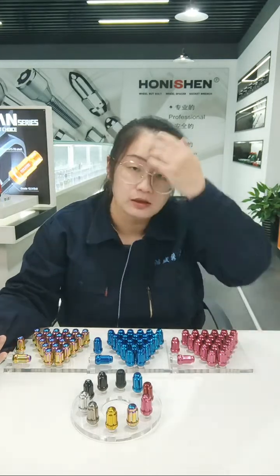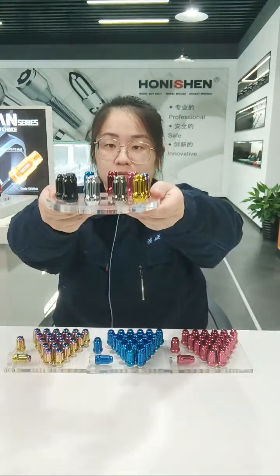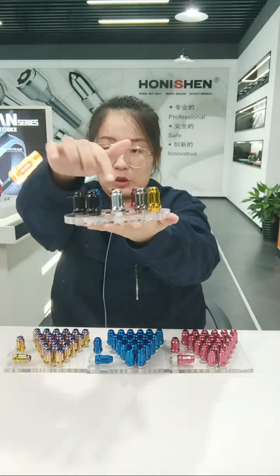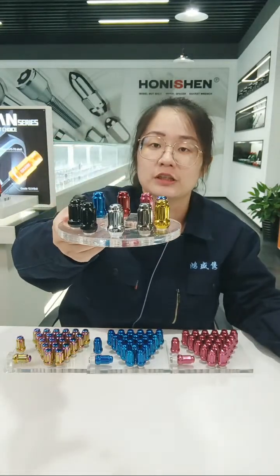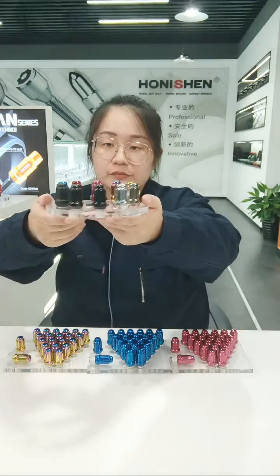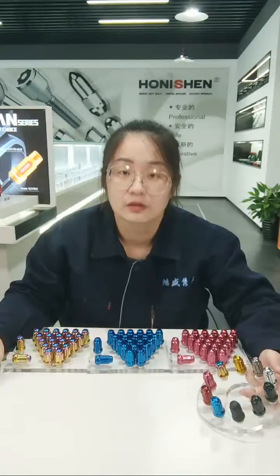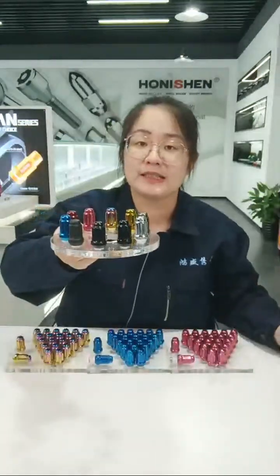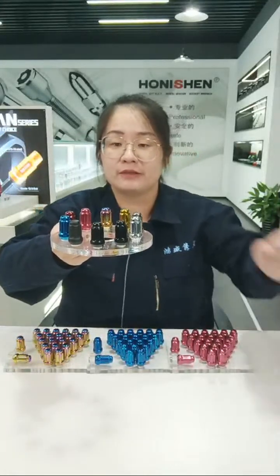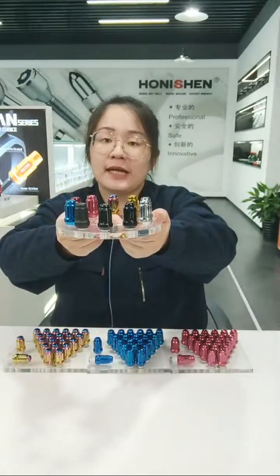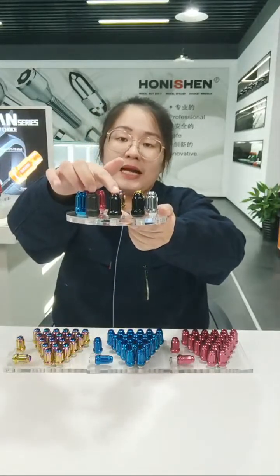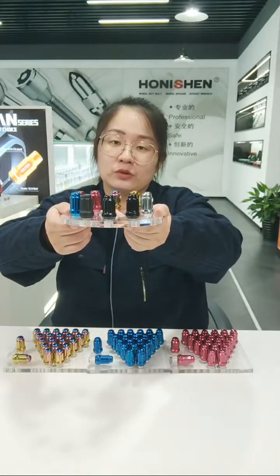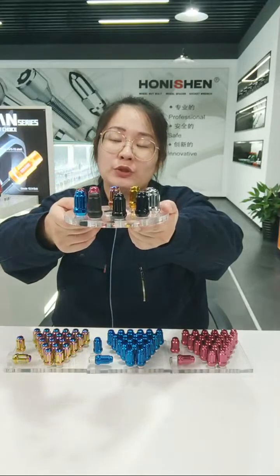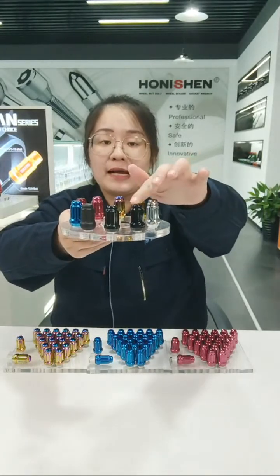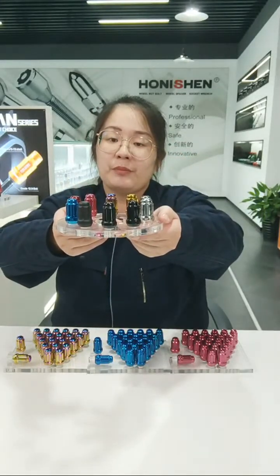For the aluminum cap, we have different colors, and for our steel nuts, we also have different colors. This is chrome, and our chrome could pass over 72 hours salt spray test. And there are 3 blacks here. There are 3 differences between these 3 blacks. First, the anti-rust performance is different. This is black chrome, and it could pass over 96 hours salt spray test. And this is black electrophoretic. It could pass over 48 hours salt spray test. This is matte black. It could pass over 200 hours salt spray test.